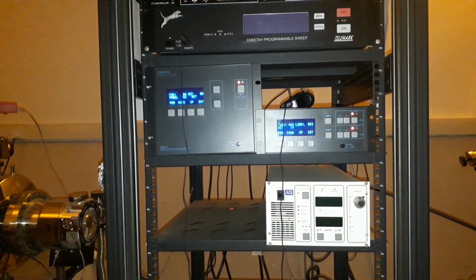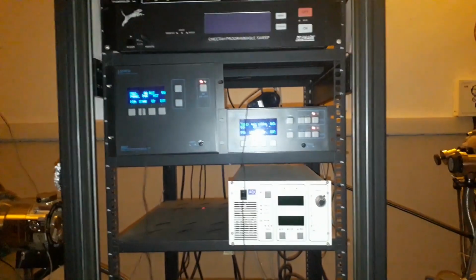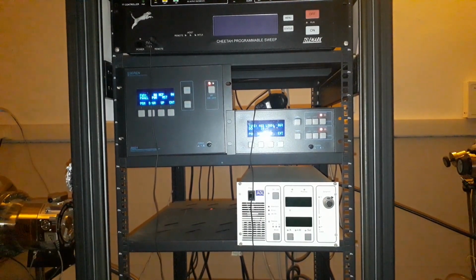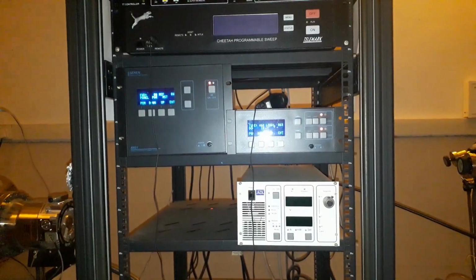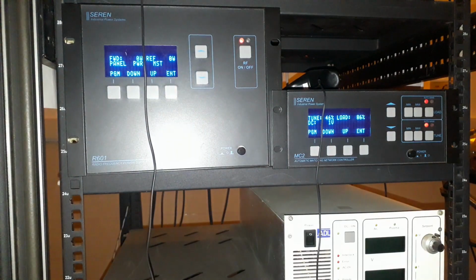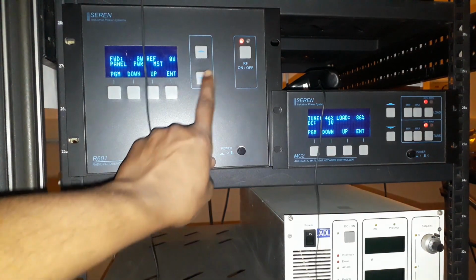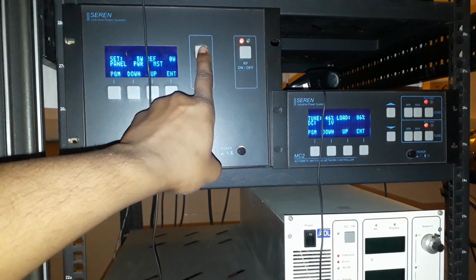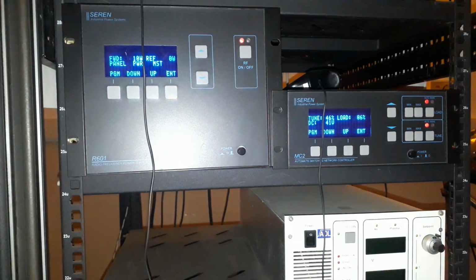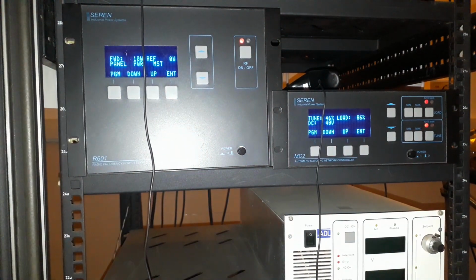So it's saying 0 watt. Reflected is zero and something like that. I'll look around and there is no plasma. So I'm going to increase the power up to 10 watt and we'll see the corresponding values. So I'll go to 10 watt and reflected is 0 watt. DC is 40 volt, which is pretty good. And let's see in the plasma chamber what is happening there.